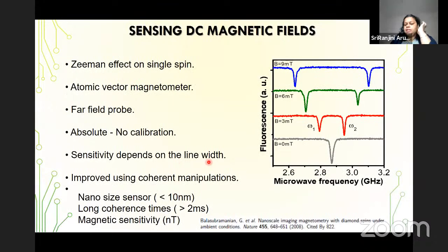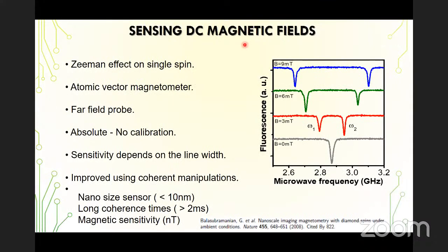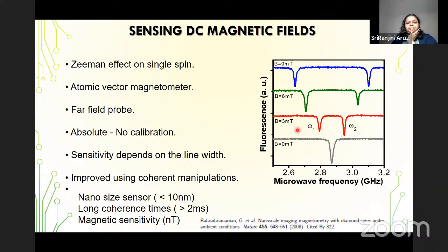So what we do with this, we can sense DC magnetic fields. Here it's a very classical example of looking into a single Zeeman effect splitting in the single spin. This is what I showed you earlier with applying microwave frequency. We can actually look into this difference between the bright and the dark state. But when we start applying an external magnetic field like 3 millitesla, 6 millitesla, 9 millitesla, you can see the Zeeman splitting goes up as the strength of the magnetic field is increased.